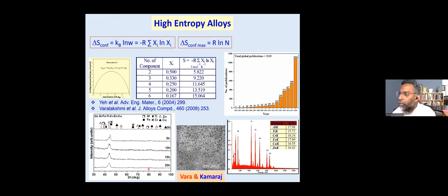And what is also beauty here is you can make them in a nano form. Because of the ball milling that I do, the powder particles break and become nano, and each of these black dots that you see is one particle of such a high entropy alloy. Okay, how do I know that this is a high entropy alloy? I can put my electron beam in a SEM on each of these black particles and collect a spectrum called energy dispersive spectrum and analyze the composition.